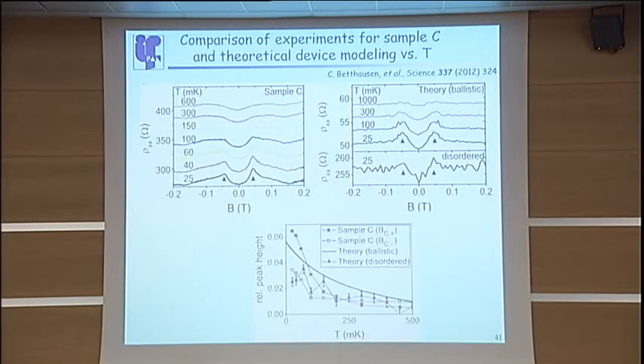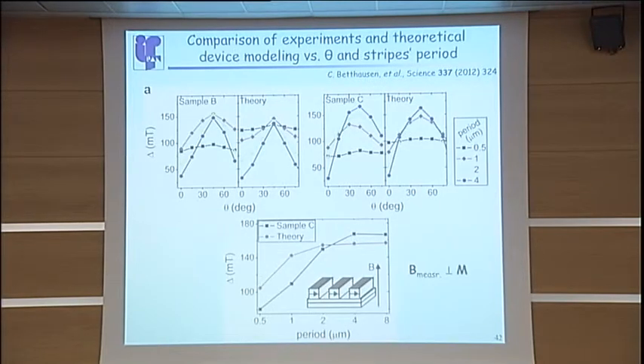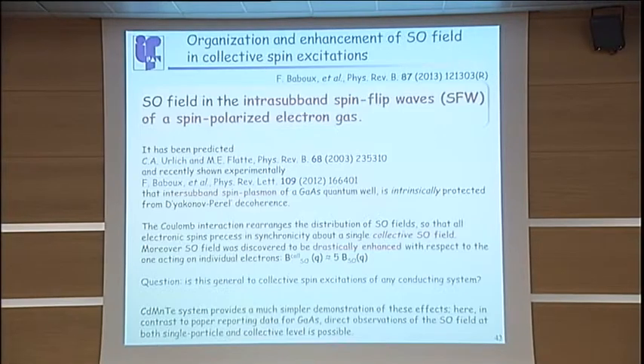I only want to show you that the theory describes the experimental data quite well. So this is experiment, this is theory, and please note that both for ballistic and disordered systems, those data are quite well reproduced. Also, they have performed calculations versus angle, and again, here is the experiment for samples B and C, and here is the angle dependence.